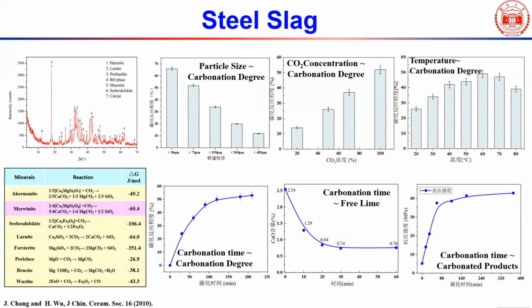Because now a lot of people try to carbonate steel slag to make lightweight aggregates. Steel slag has a density of about 3.8 or 3.9. Limestone or regular coarse aggregate has a density of about 2.6. And so you try to use such a heavy material to make lightweight aggregate. That's one question.